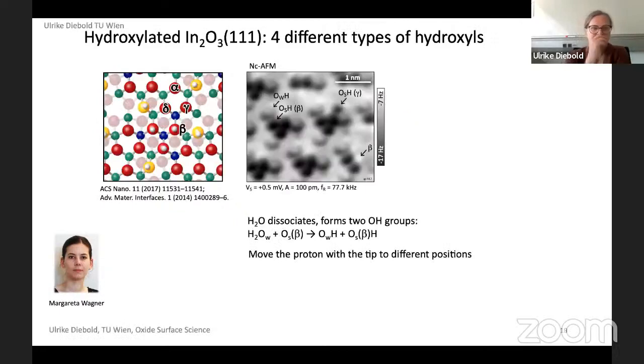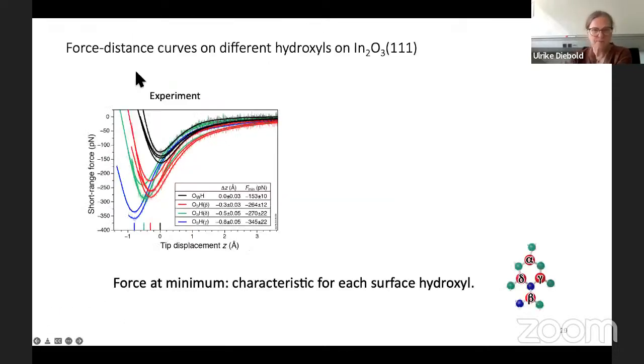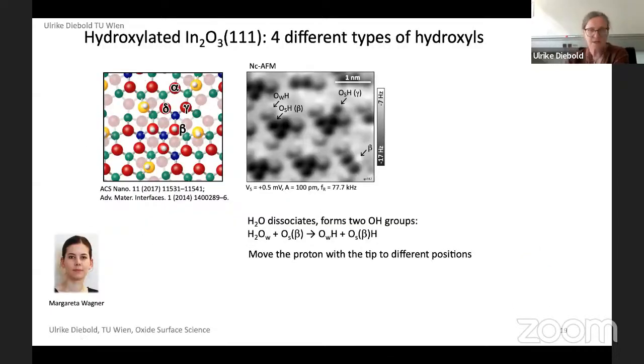All right, so we can image this surface. We can make the surfaces really beautiful and nice. And then we put a little bit of water vapor into our ultra high vacuum chamber. And then what happens is that the water dissociates, like I showed you in this movie before. A water molecule comes down, dissociates, and the proton goes to an oxygen atom. These, which look like propellers, are always two different OH group hydroxyls. One is the water hydroxyl. So water comes, there's a surface oxygen atom, let's say the one here. The water molecule dissociates and gives the proton to this surface hydroxyl. You have two protons and you can distinguish them really nicely in these beautiful images.